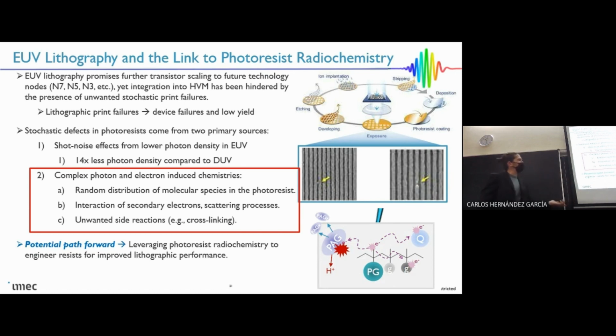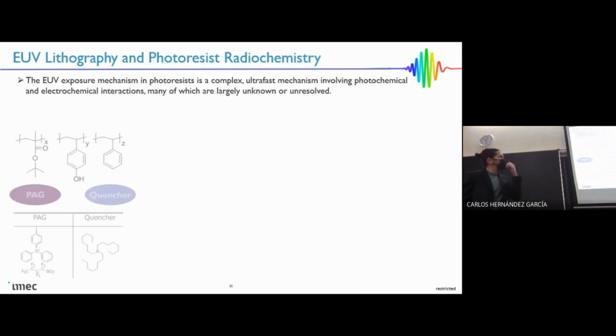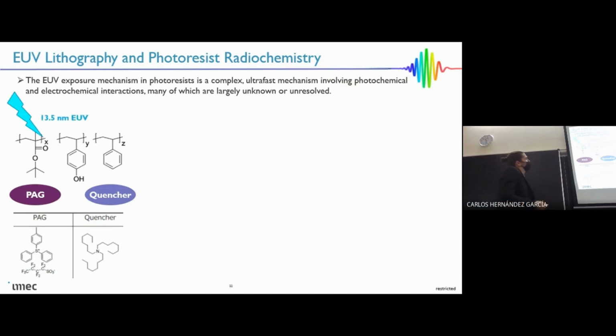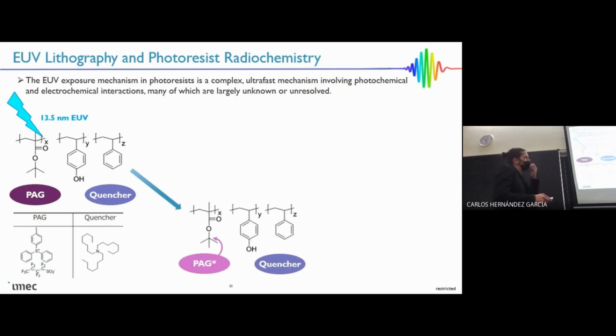So the idea for a potential path forward is to leverage the radiochemistry, and then we can engineer these photoresists to respond more appropriately to EUV light, giving us better performance for lithography. If we take what looks like a typical photoresist, a polymer material, a blend of different polymers, it has additional chemical agents added called a photoacid and a quencher to help initiate the reaction. So when we shine the EUV light in, what we would really like is to photoexcite an acid that's going to remove a part of one of the polymer chains. That's going to cause a solubility switch, changing its solubility in a solvent.